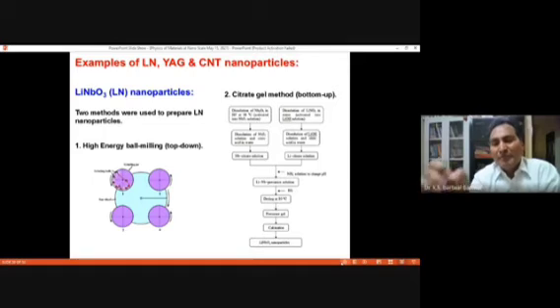Similarly, when we start from niobate or carbonate or sometimes any other salt, and use a chemical reaction, the citrate gel method, finally we have nanoparticles of lithium niobate. So starting from carbonates or hydroxides, we get nanoparticles of lithium niobate. This is the bottom up: starting from the lithium atom and niobium atom, then getting lithium niobate. And here we have bulk lithium niobate, and then reduce the particle size from micron to nano. So this is the top down, and this is the bottom up technique.